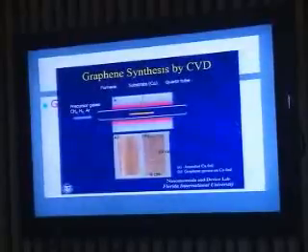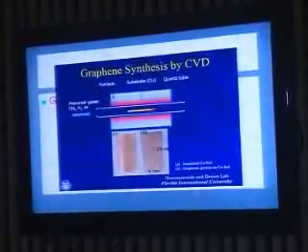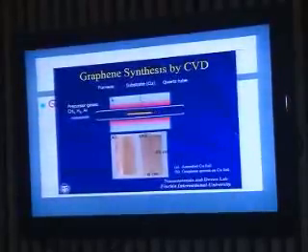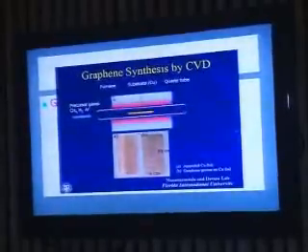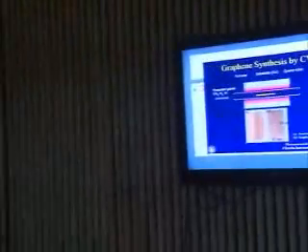Then we found that pristine graphene is not helpful because the switching on and off is quite tough. So we want a slightly non-zero band gap. How do you do that? That takes us to the band gap engineering using density functional theory. If you put a boron atom there or a bismuth doping, then its band gap is no longer zero. Switching on and off becomes easier. So, we are counting on boron doped graphene, bismuth doped graphene.